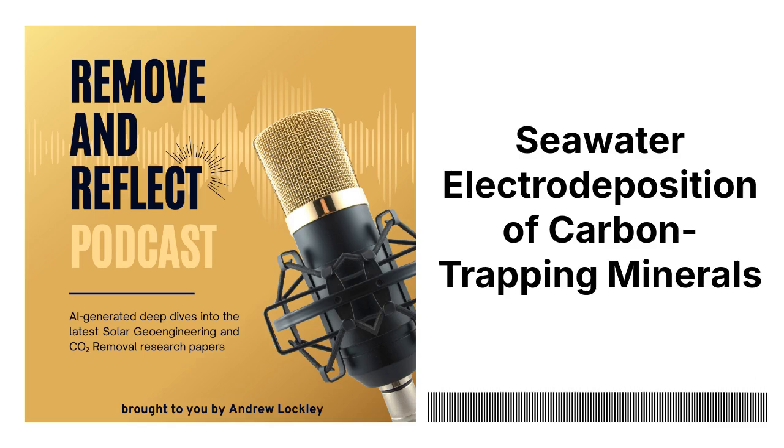Exactly. So when the oxygen reduction reaction was dominant, which happens at lower voltages, they got very little mineral. Oh, wow. And what they did get tended to stick really tightly to the electrode surface. Okay. But when the water reduction reaction took over at higher voltages, they saw a much more substantial mineral yield. Interesting. Although at very high voltages, the vigorous bubbling of hydrogen gas could actually cause some of that mineral to detach from the electrode. Oh, that's interesting. I guess that could be good or bad depending on what you're trying to do. Exactly right. If you want to collect the minerals, maybe that's a good thing. But if you want it to stay on the electrode, maybe not so much.